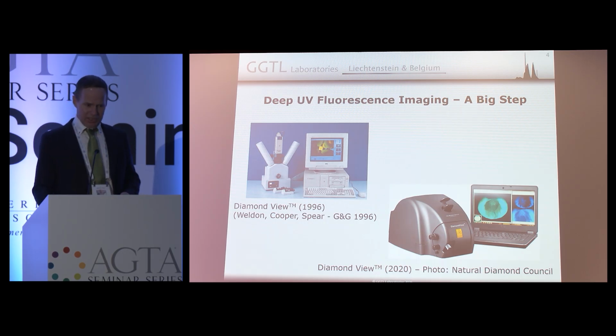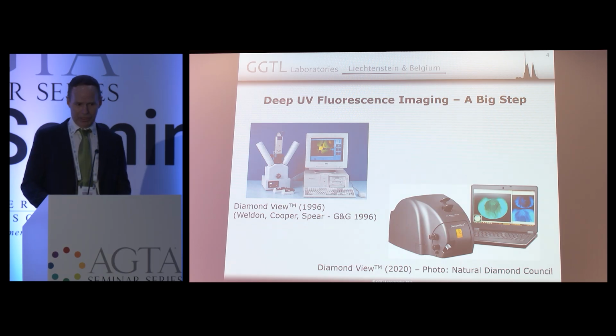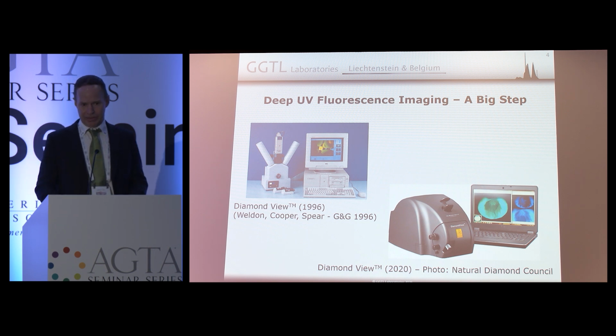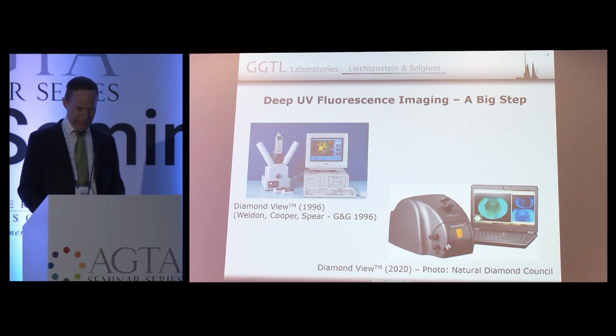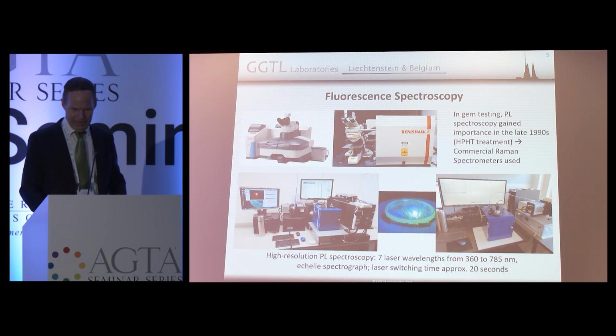And this device was actually built mainly for the detection of synthetic diamonds, because in those diamonds you can visualize the patterns much better at deep UV excitation than any other UV excitation. At least that's true for colorless synthetics and for blue synthetics. And that was a really big step.